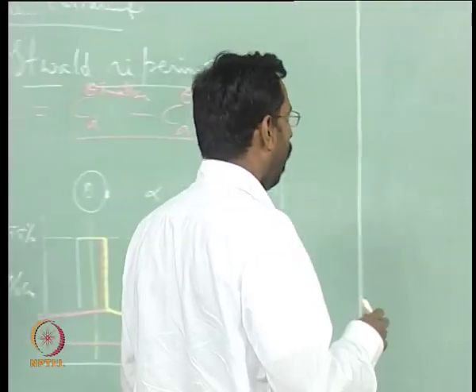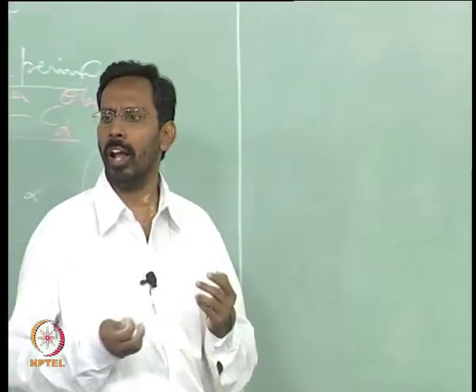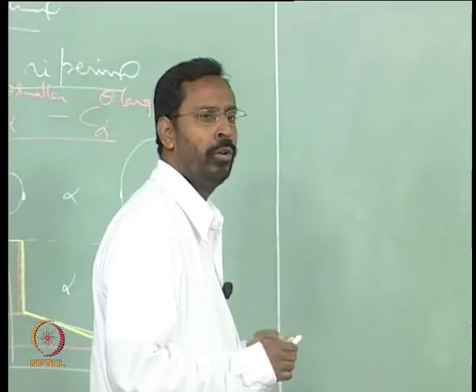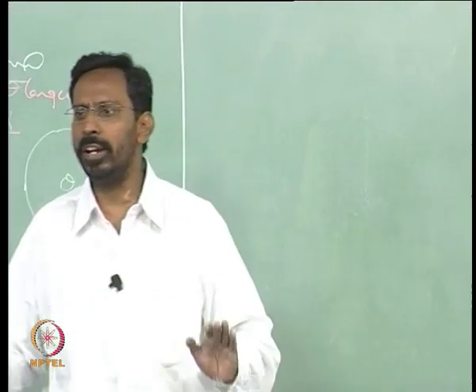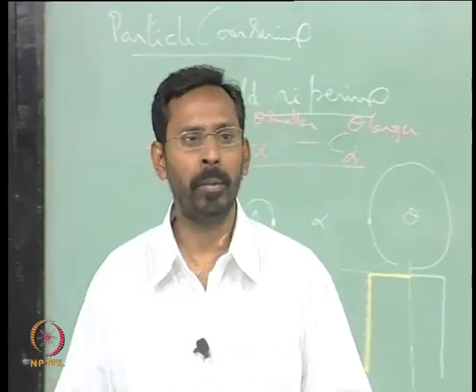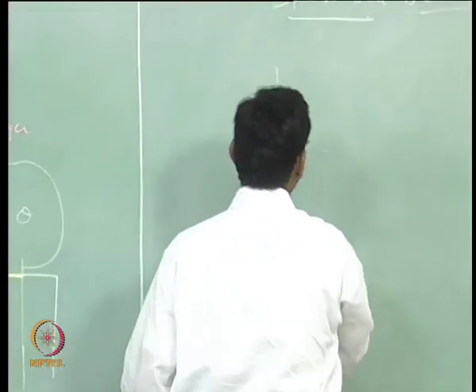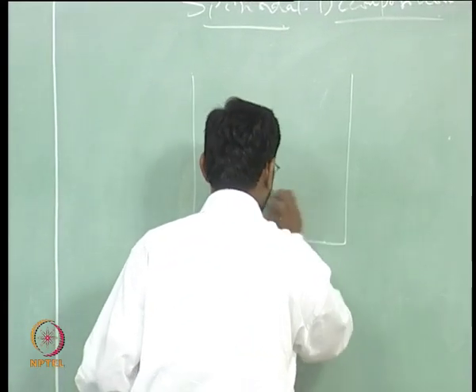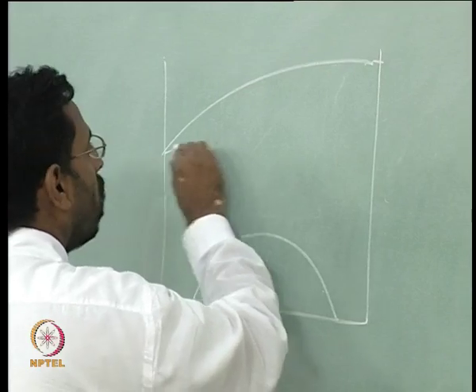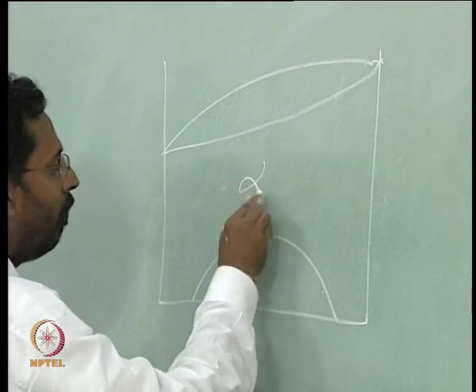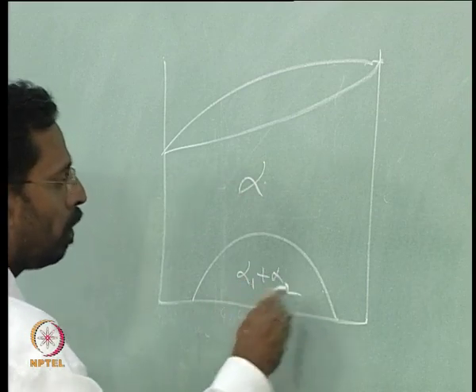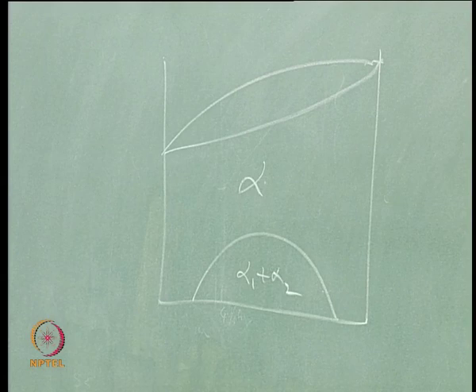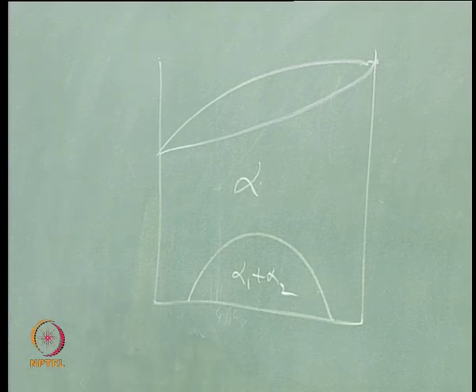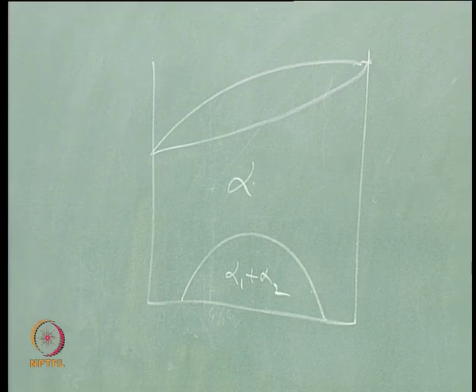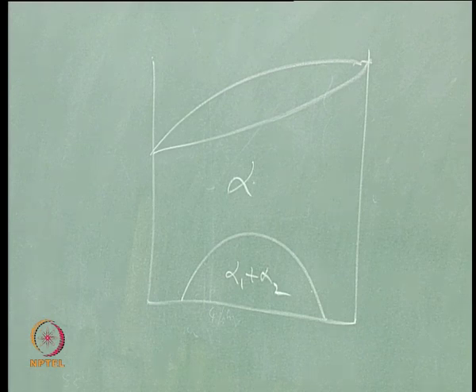Let us try to understand that, and you will see that spinodal decomposition always occurs when the phase diagram shows a miscibility gap. When there is no miscibility gap in the phase diagram, you will never see a spinodal decomposition. So, let us try to consider a phase diagram with a miscibility gap. Something like this, alpha splitting into alpha 1 plus alpha 2. Okay. And whenever you talk about spinodal decomposition, you need to consider one aspect of stability. What is the stability?